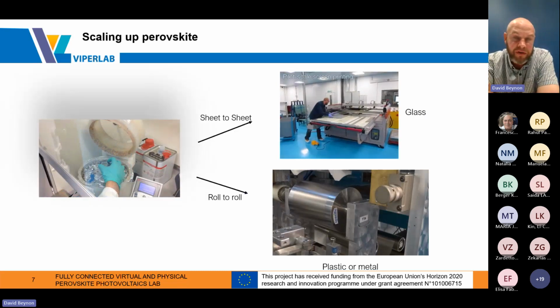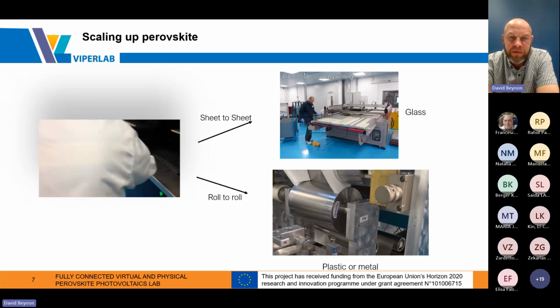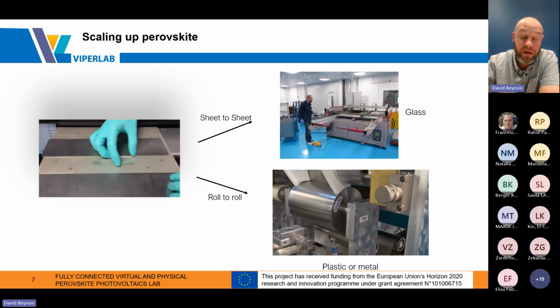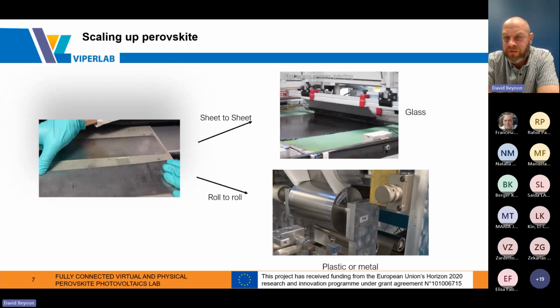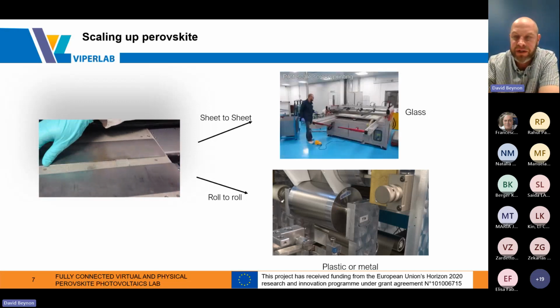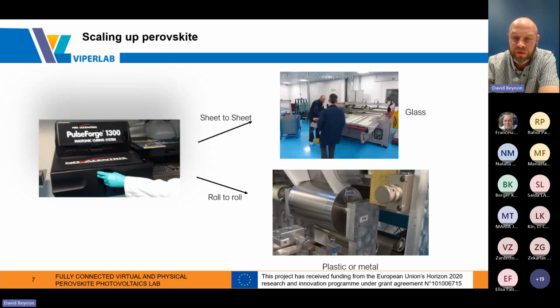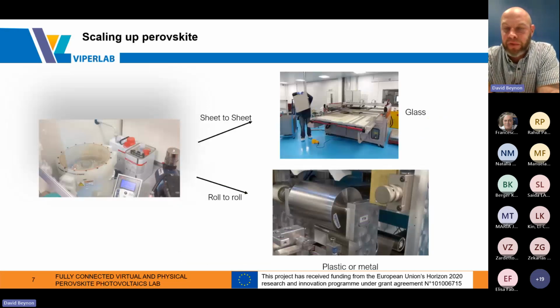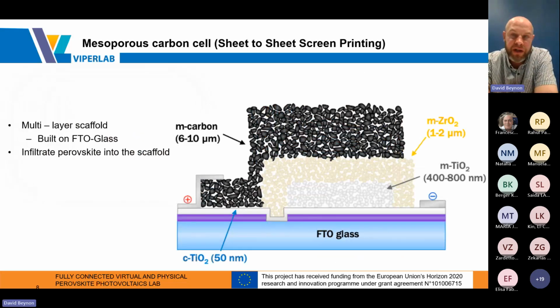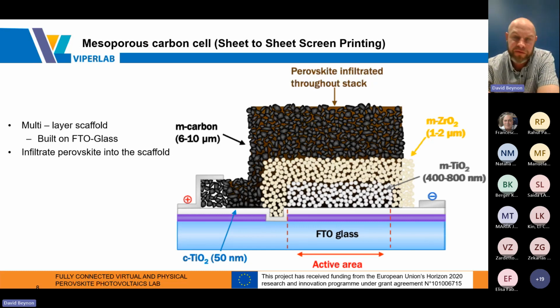So our philosophy for scaling up. So we're going from the lab scale spin coating. We're scaling up to 2 methods: sheet to sheet on glass-based devices, and roll to roll on our flexible devices. So our sheet to sheet scale up through screen printing is through the mesoporous carbon cell. So this is a cell where we print multiple layers using screen printing. Use high temperature processing in between, and infiltrate the stack with perovskite to complete the device.